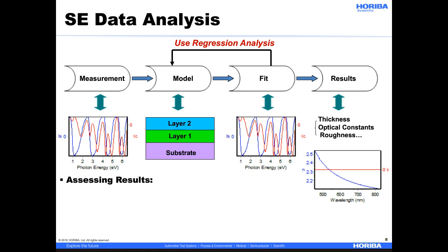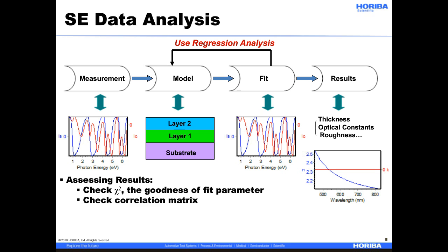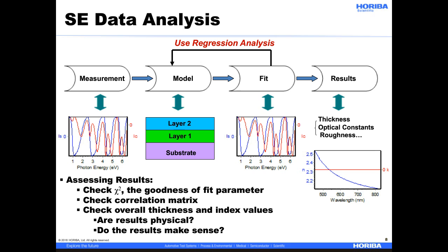A lot of times we get the question, how do I know if I have a good model? As far as assessing the results, you can check chi-squared, which is the goodness of fit parameter - that'll tell you how close your model matches your data. You can check the correlation matrix, which will tell you if any of your fit parameters are correlated to each other. Typically thickness and index can be correlated, so if there's a way that you can decorrelate certain parameters, you should certainly do that. And then we check the overall thickness and index values - we ask, are the results physical, and do the results make sense?